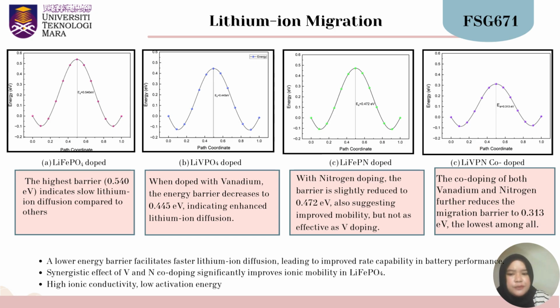The biggest improvement is when both vanadium and nitrogen are added together, co-doping. The barrier decreases a lot to 0.313 eV. This happens because the structure relaxes and the diffusion path becomes wider, making it easier for lithium ions to move. Because of this lower activation energy, the co-doped LiFePO4 shows high ionic conductivity, meaning the lithium ions can move faster. This is important for quick battery charging and discharging.